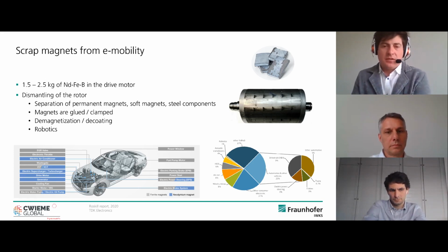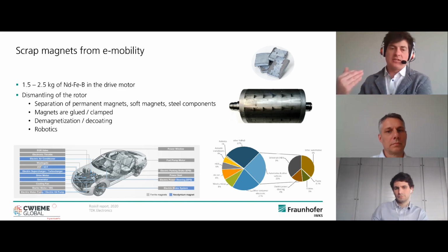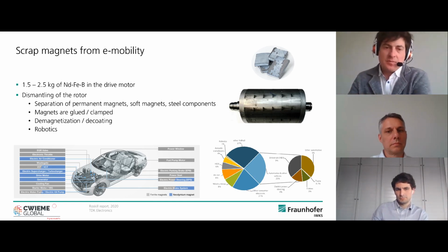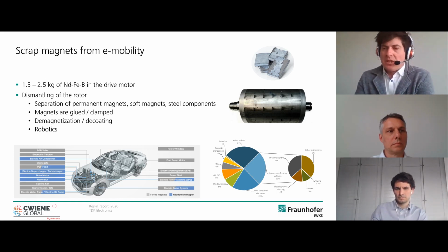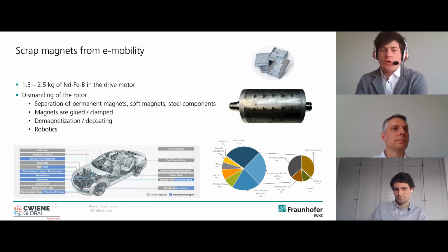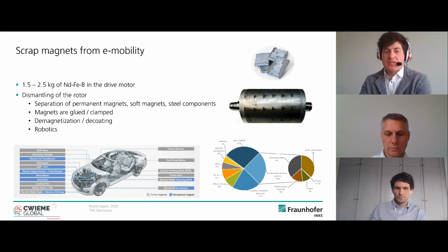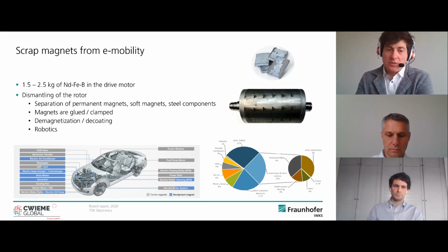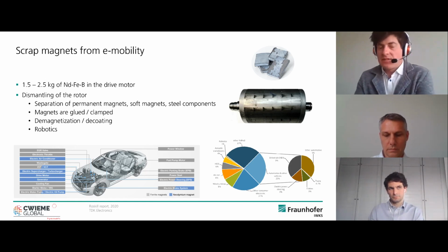So nowadays, these devices were recycled together with the main element, iron. And the pretty precious rare earths, they were just lost because they get oxidized and they can't be used anymore. So the separation is key for us. Here we are checking and doing research on how to get out the magnets as automated as possible. We are starting to use robotics for that. And also the demagnetization is important. In which state is the magnet demagnetized? Do I have to heat up the whole device? Can I just heat up the magnets? How can I deal with the polymers inside? This material is most of the time some glue. Some of the magnets are also clamped, and so different kinds of devices.